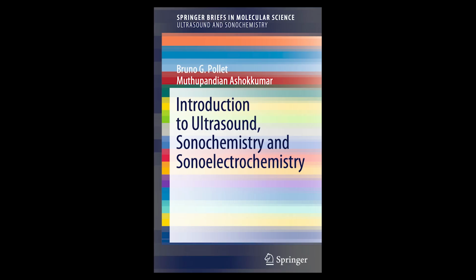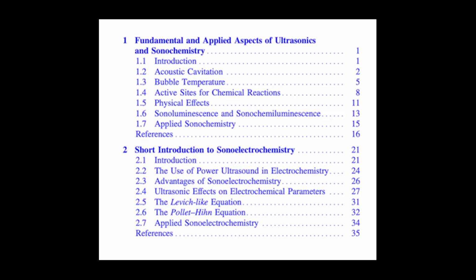First, there's the gas phase zone. This is the true interior of the collapsing bubble, the core. This is the hottest part, the pyrolysis zone, where temperatures might indeed reach that upper range, maybe 5,200 to 6,500 Kelvin, and pressures around 500 atmospheres. This is where volatile molecules are torn apart. Okay, the super hot core, and the second zone?